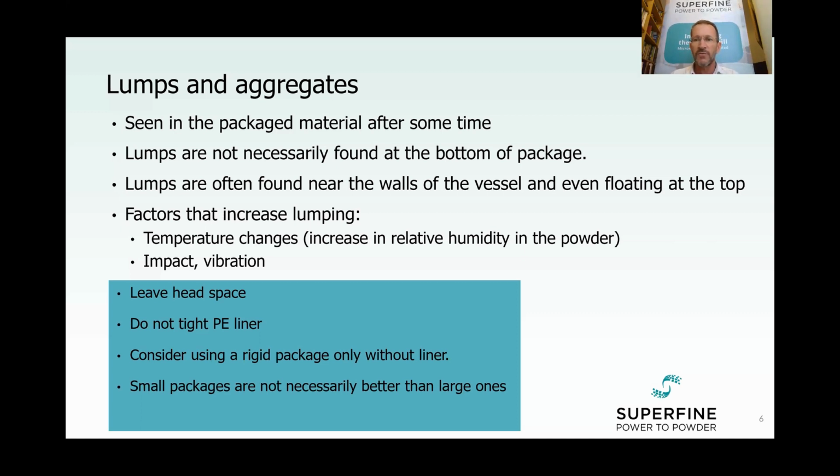Although, you know, there's no weight for the powder, it's very light, there is nothing inside, but still it was. And then we realized that most of the pressure was coming from the polyethylene liner. And in that case, we decided to not use the polyethylene liner, to put the material directly in a plastic box, and it really solved the problem. Because indeed, the polyethylene liner was applying most of the pressure.